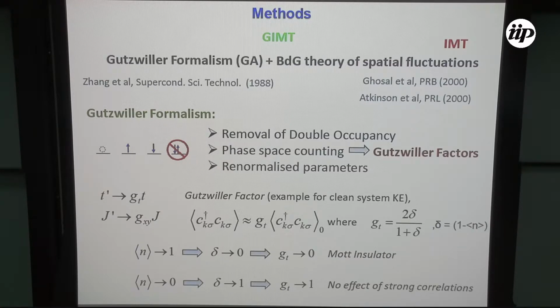This Gutzwiller factor happens to be given like this, which is 2 delta over 1 plus delta, and delta is the doping in the sample. So let's look at what is being done here. If we are at half filling, that means the density of electrons is 1, the doping is 0, so this factor is 0. That means you have no hopping in the sample. You mimic the Mott insulator nature.